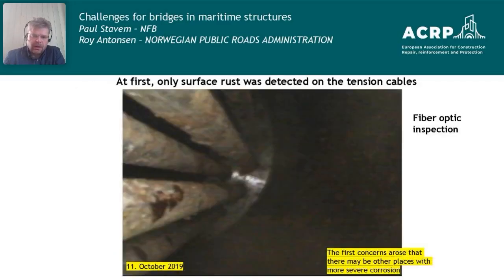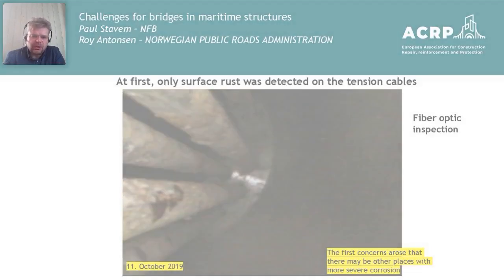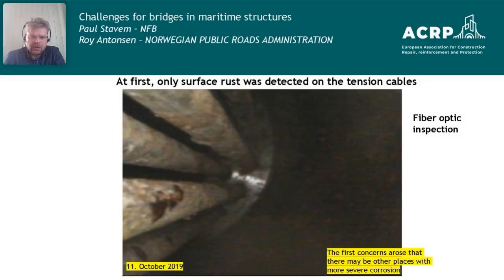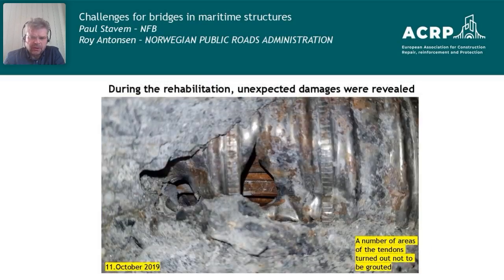A key factor there was that it was very important for us to examine immediately what about these non-grouted ducts we found, right? And here's the fiber optical analysis. This is within that steel box I showed you there, that was not grouted, and this fiber optical inspection showed first only surface rust on the steel wires there, but it gave us the first concerns that maybe there are other places inside of this bridge where we have voids and empty spaces and corrosion of the tendons. And it's hard to inspect these tendons, because, as I will show you later, here's another one, right? You can see the ducts, and the tendons are inside the ducts that are pre-stressed, right? And it's hard to inspect them because these are metallic ducts, and there are only a few methods available which are non-destructive to inspect such voids, right?